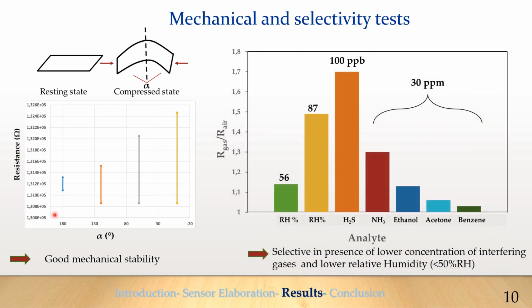Finally, the MoSe2-Mo2C sensor was also exposed to humidity and different gases and volatile organic compounds like ammonia, benzene, ethanol, and acetone to check the sensor's cross selectivity at room temperature. The sensor performed the highest response value to 100 ppb of H2S compared with the other tested gases at concentrations lower than 30 ppm of interfering gases. Moreover, the MoSe2-Mo2C sensor has a poor selectivity in the presence of high humidity or high concentration of interfering gases.